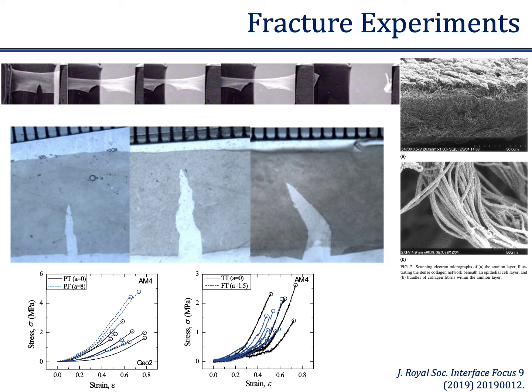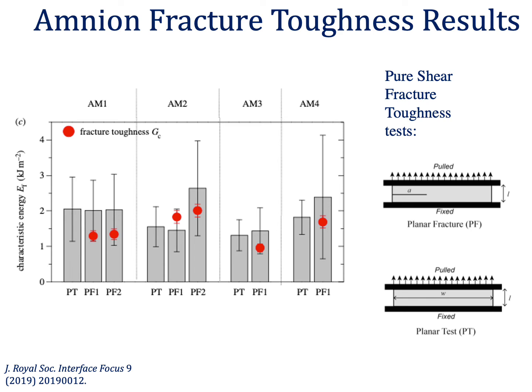So the mechanical response is relatively notch insensitive, which is an indication of just how tough the tissue is. When we look at the quantitative fracture results, we see that we get a pretty substantial fracture resistance value, or 1 to 2 kilojoules per meter squared. And this is pretty comparable for some other soft tissues, as we'll see in a moment.